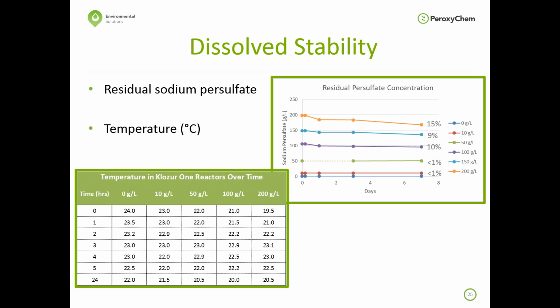In terms of after batching it, Klozur One is very stable. This is one of the things that we've worked very hard to achieve. In the top right graph, you can see that at different concentrations, again going from 0 to 200 grams per liter, the lower concentrations over a 7-day time frame, very little Klozur One degraded, less than 1% degraded over that